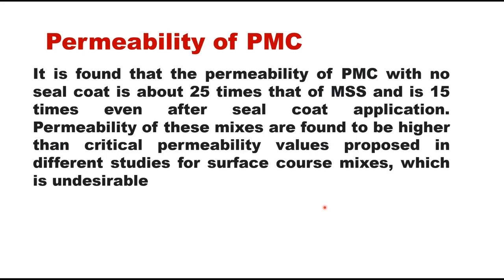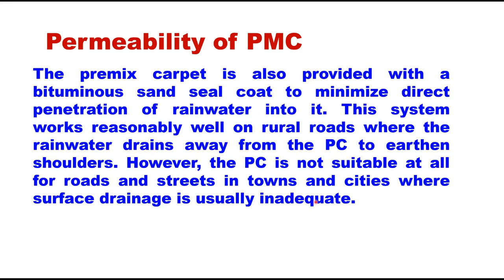Permeability of premix carpet without seal coat is about 25 times that of mixed seal surfacing, and 15 times even after a seal coat has been provided. Permeability of these mixes is found to be higher than critical permeability values proposed in different studies for surface course mixes, which is undesirable. Therefore, premix carpet is provided with a bituminous sand seal coat to minimize direct penetration of rainwater. This system works reasonably well on rural roads, but PMC is not suitable for roads and streets in towns and cities where surface drainage is usually inadequate.